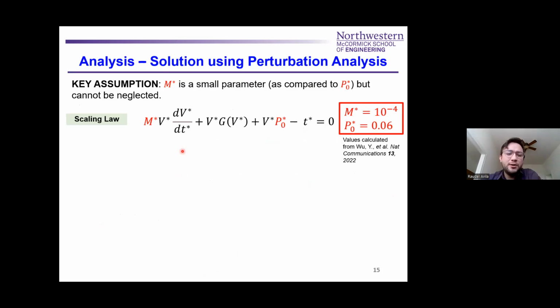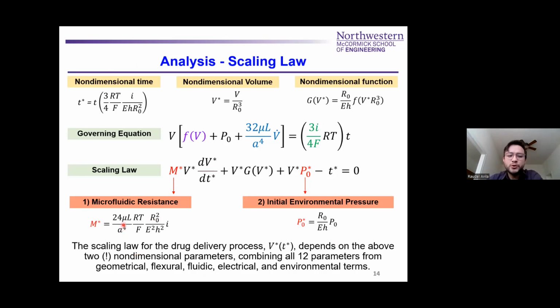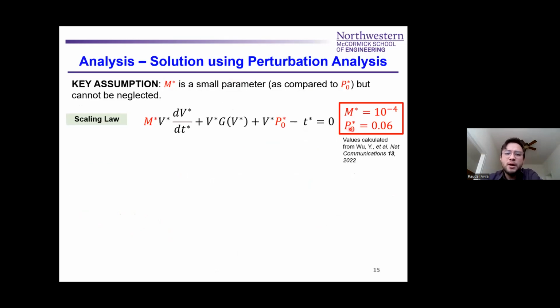Now, how do we solve this ODE, and what are the solutions? Here we have to make a key assumption, and that is based on the values that we measured from the experiments. If we go back to our terms, we can actually compute what these parameters are going to be based on the device that we have. And we find that M star is a small parameter compared to P0 star. This means that M star is 2 orders of magnitude smaller than P0 star. That means that we can use perturbation analysis to solve our scaling law. First, we can find our solution without the flow resistance, so we assume that M star is 0.